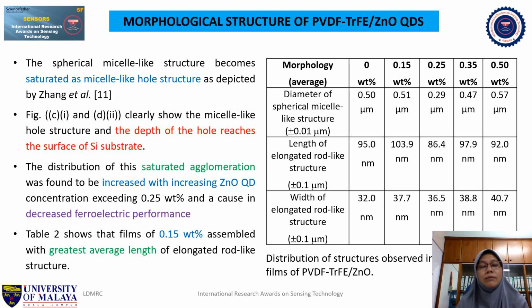So the distribution of this saturated agglomeration increases with increasing zinc oxide quantum dot concentration exceeding 0.25 weight%, and causes a decrease in ferroelectric performance. So in this figure, we can see that the 0.15 weight% sample has the greatest average length of elongated rod-like structure, which probably contributes to the highest pyroelectric and ferroelectric properties.